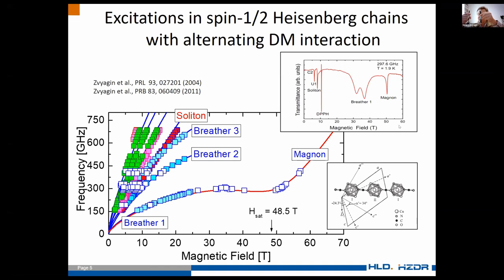So we have spin up, spin down, spin up, spin down. But if you have a kind of alternation because of an alternating g-tensor or Dzyaloshinskii-Moriya interaction, basically we break inversion symmetry, and instead of that pattern, we have just a small tilting. And this tilting completely changes the picture. What is interesting is that the excitation spectrum for such a system can be described using the so-called sine-Gordon model, combined with quantum field theory. And this theory predicts the presence of solitons and antisolitons, instead of spinons.